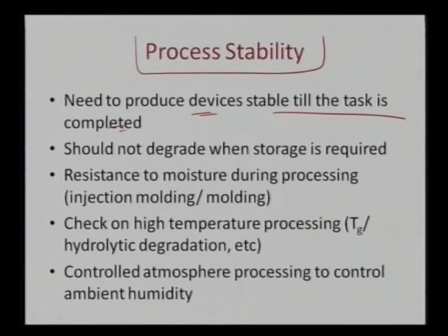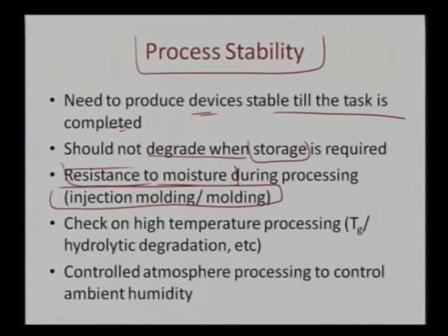So they should not degrade when they are supposed to store the particular drug. Again, they should be resistant to moisture when they are being processed, because during processing it should not start degrading there itself. Processing is occurring at much higher temperatures, like in injection molding or compression molding, so they should be resistant to moisture, because if there is some moisture uptake, they can start degradation.